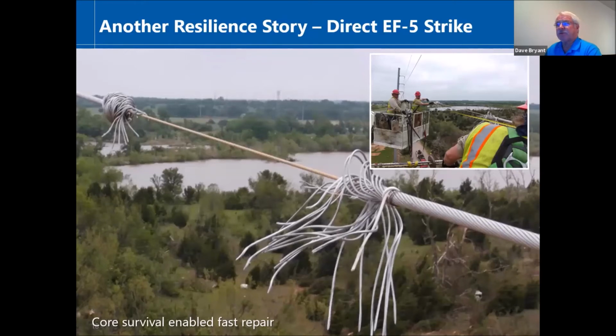This picture shows damage that happened to the conductor strands after being hit directly by an EF5 tornado in Moore, Oklahoma. I think winds in this zone were measured at about 220 miles an hour. This was a new line running north-south from a generation facility that was about half a mile south of where this picture was taken. They mounted this on steel monopoles about 125 feet above grade. An oil tank was picked up by the wind, slammed into a steel monopole, and knocked it over to about 45 degrees. The shock wave actually caused these fully annealed aluminum strands to snap.